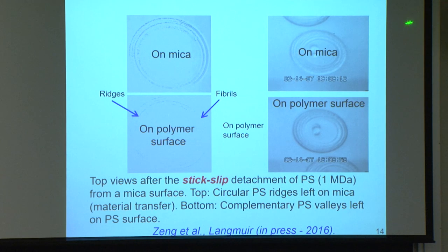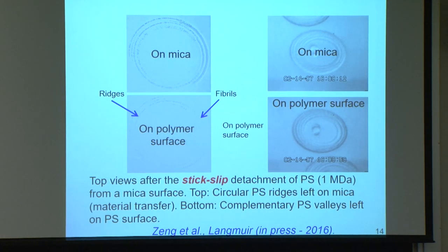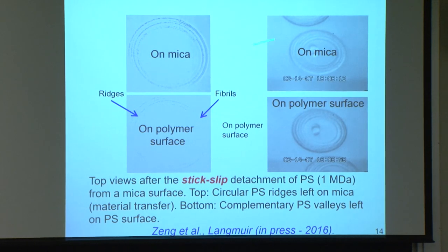And if you look at the other surface after separating, that's a polymer surface. On one surface you see ridges where polymer has been transferred. On the other one, you see valleys, exactly because that's where it's been transferred. But the most interesting thing is you notice that there are rings.